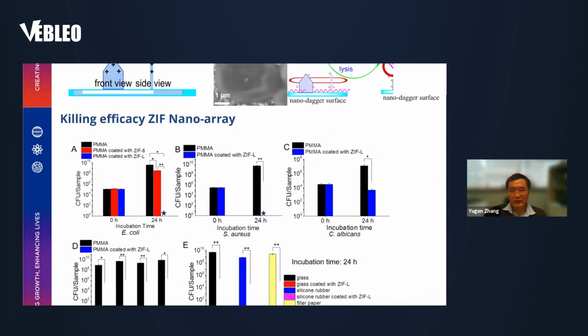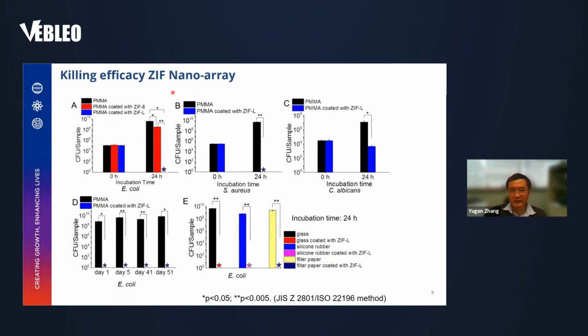Showing here is some killing efficacy of ZIF nano-arrays. This one is against the E. coli, and you can see we have 2 different types of coatings. The red one is a ZIF-8 coating on PMMA. This is the coating without nanostructure. It's a smooth layer. But the blue one is a ZIF L coating with this nanostructure, nano-array structure we just saw.